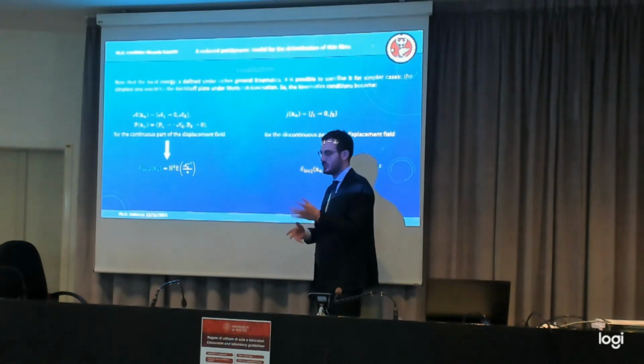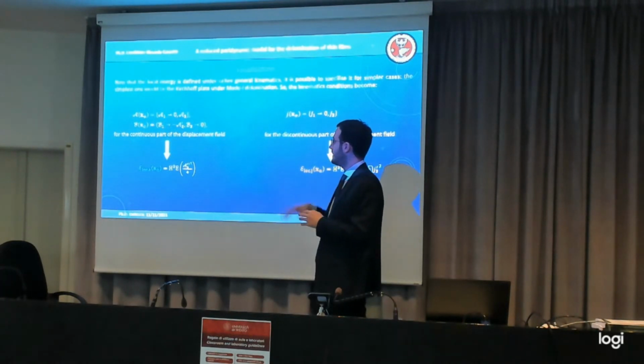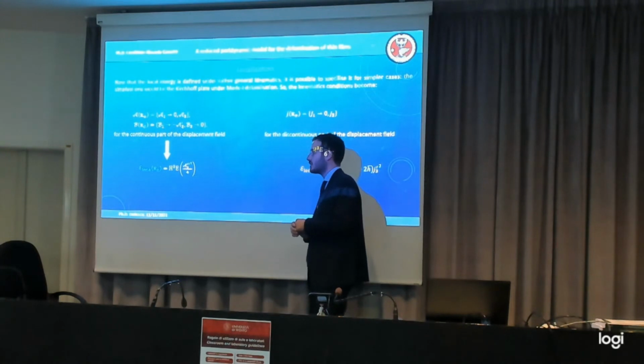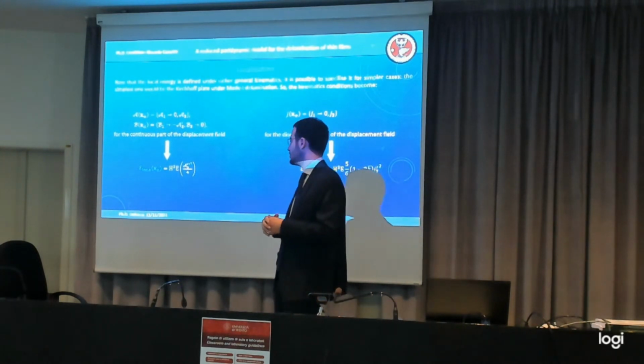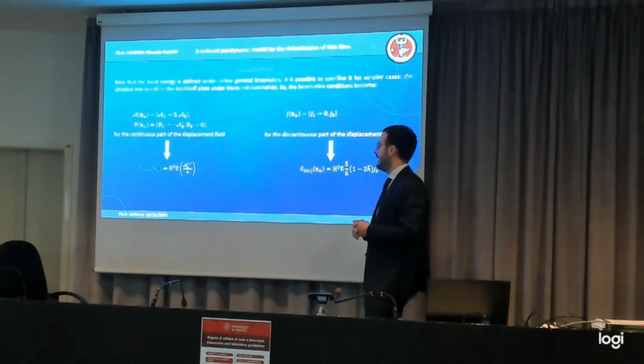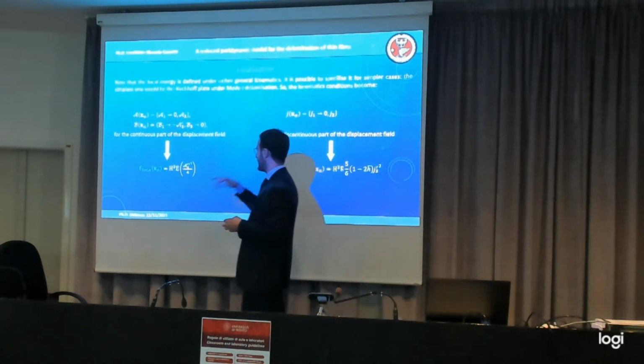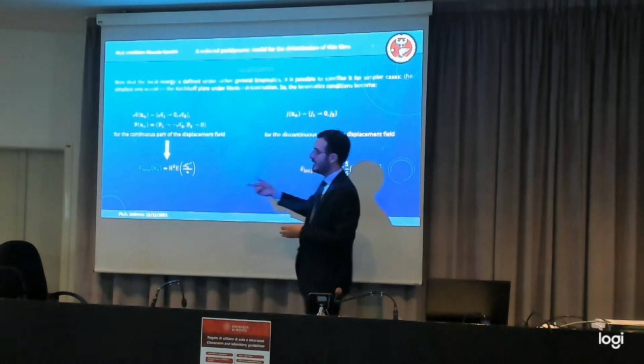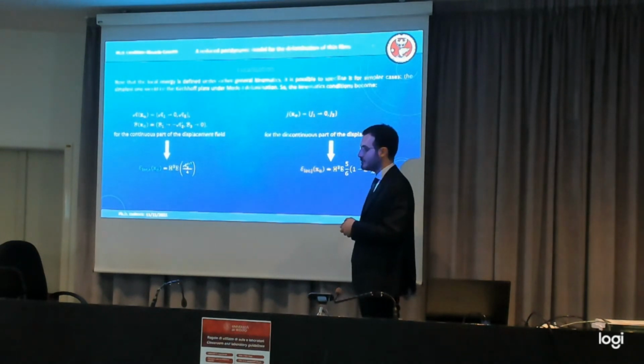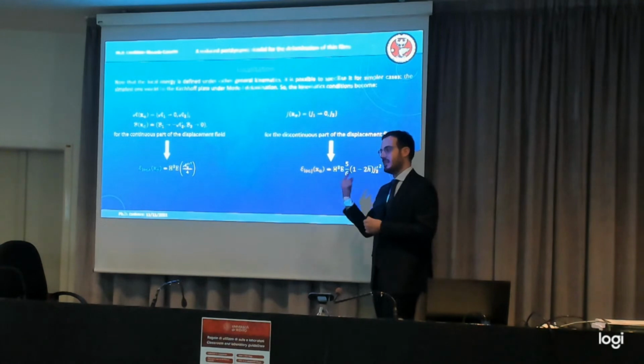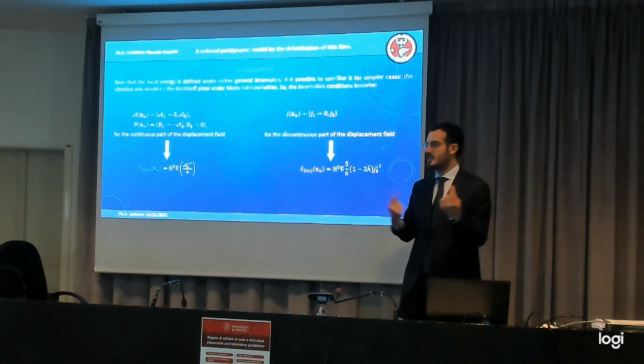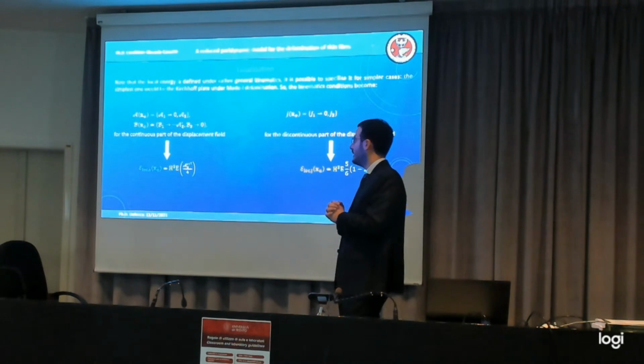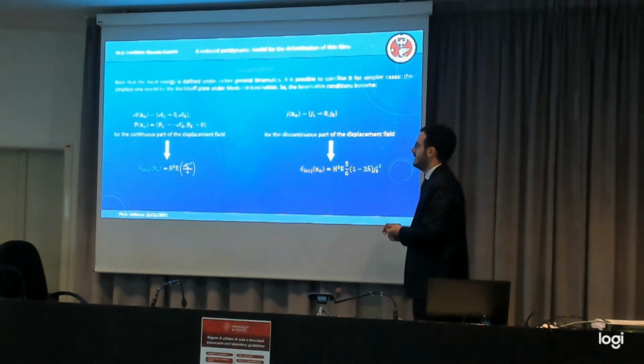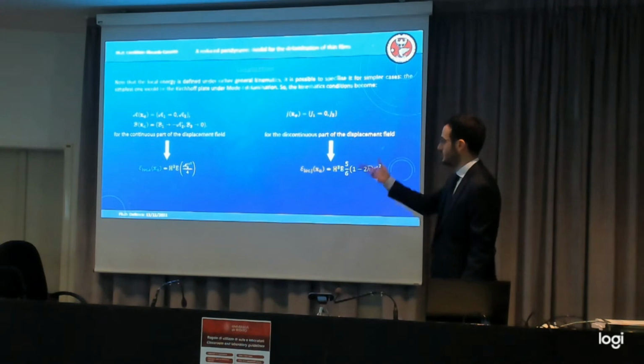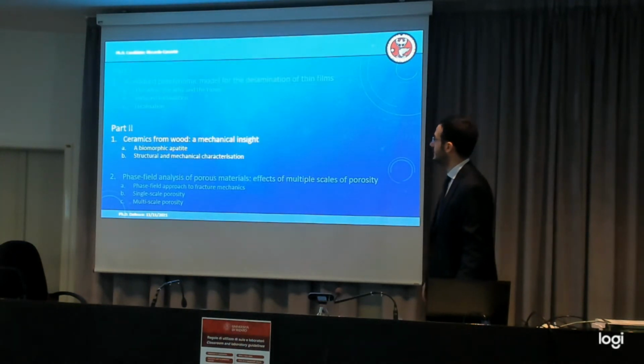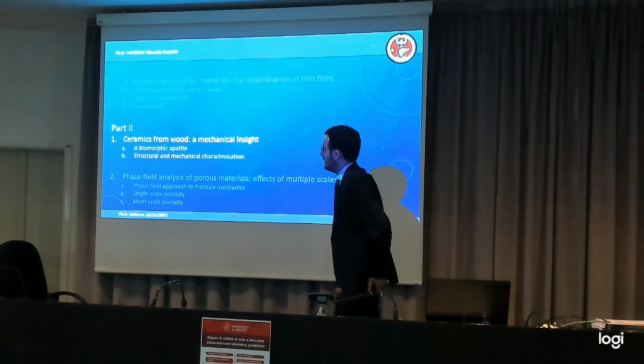If you are 3D or plane strain, the Poisson ratio is fixed to 1/4, and if you have plane stress or a 2D solution, it's fixed to another value. And the other aspect that is affecting this number is the way that you calibrate that single parameter. I said before that the best way is to make an energetic equivalence with a local elastic model, but there are other ways to do that. This was just a choice to obtain something that resembles what we already know from mechanics.